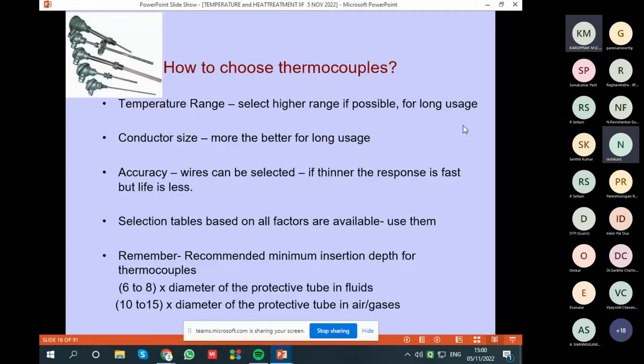And how much you should insert the thermocouple in the furnace, heat treatment furnace I'm talking, or any furnace. The standard thumb rule is about 6 to 8 times the diameter of the thermocouple. That is, if the thermocouple diameter is say 12 mm, it should be about 12 into 8, that is about 100 mm inside the furnace. If you follow that thumb rule, then the sensor measures the temperature correctly. The tip of the thermocouple is going to measure the temperature. The tip does not get affected by the deflections from the wall, and you always get the right temperature.